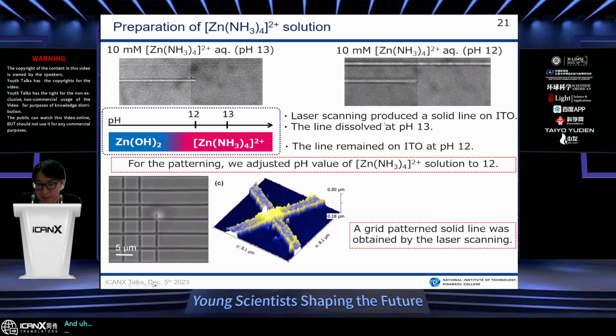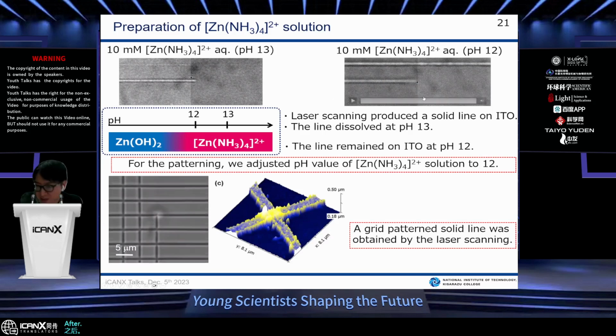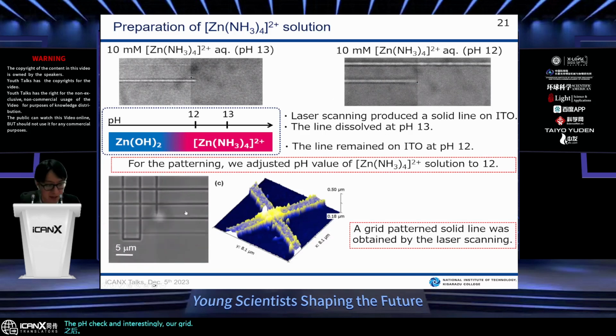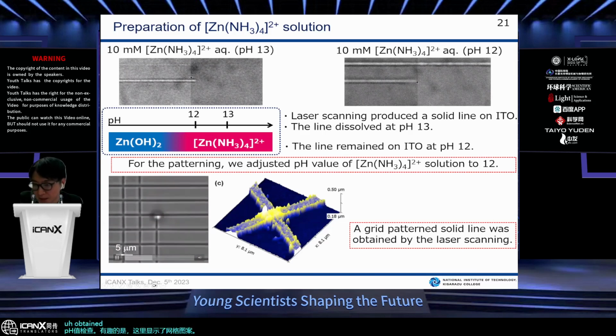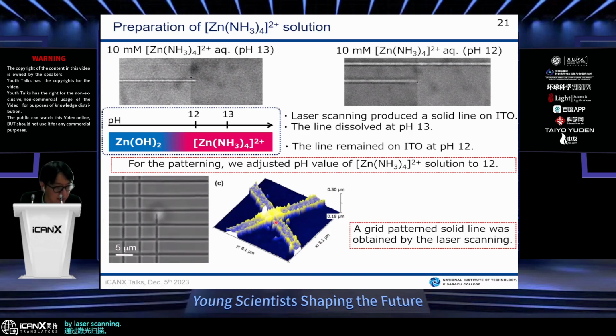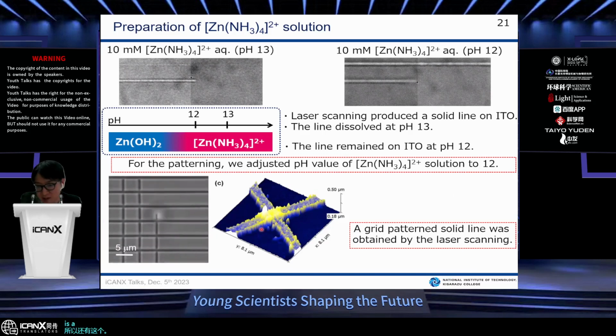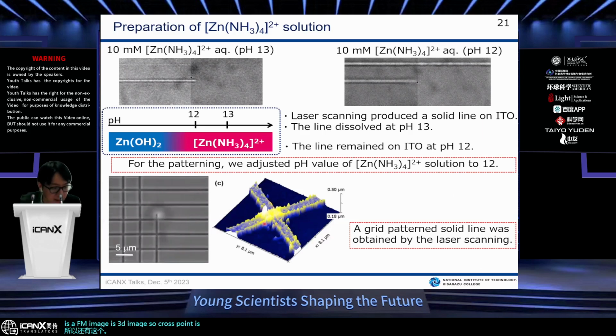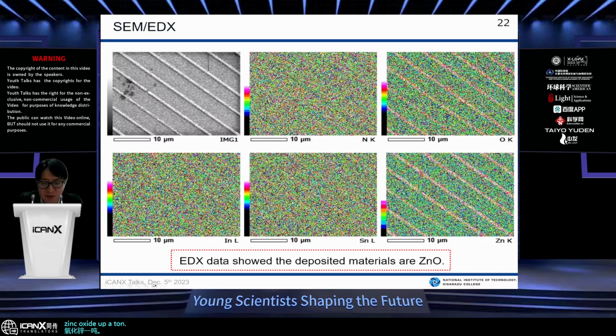After the pH check, interestingly, a grid pattern shown here was obtained by laser scanning. This is an AFM image, a 3D image. The cross point is just overlapped zinc oxide pattern. Here is the SEM and EDX data showing the deposited material. This EDX shows the deposited material is zinc oxide, from this data and this data.